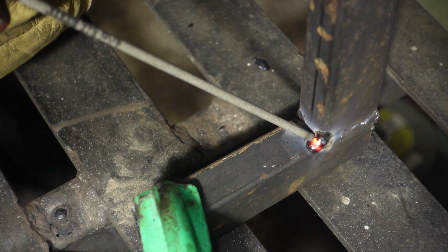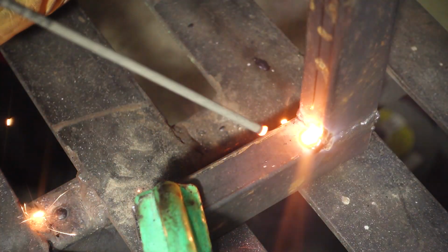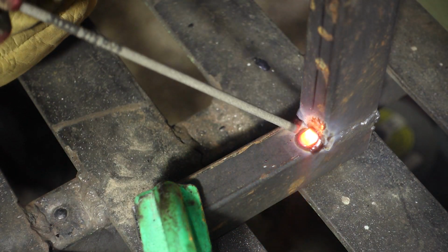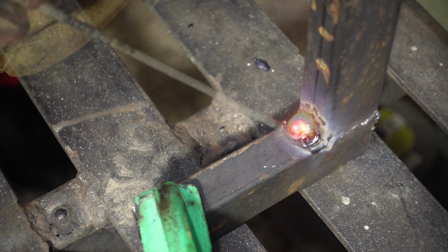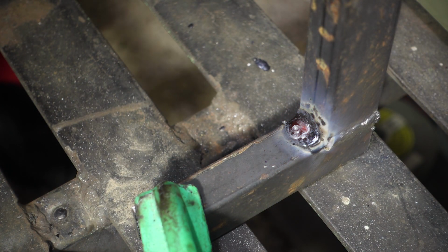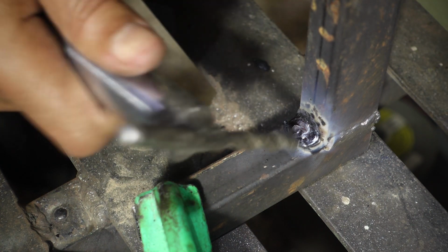When I tried to weld here at 70 amps, I wasn't in the right position. I got some slag trapped in the weld. If this happened to you, stop and clean the area and try again. These things happen, but learn to correct them the right way.